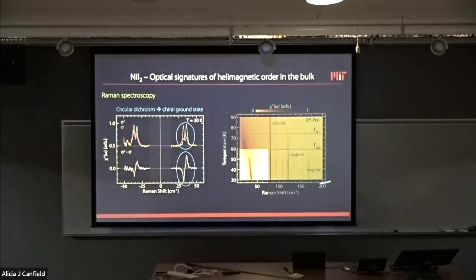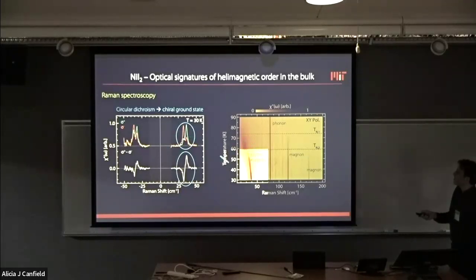So this is the more extended temperature map. You see this electromagnon that's sharp at low temperature, and then it softens towards the transition. It broadens as well. And if you look at this pair of excitations, it's actually two electromagnons. We look at it with circularly polarized light.